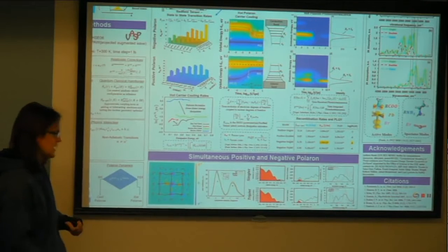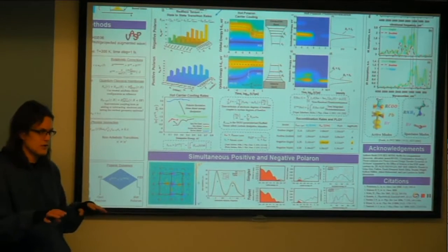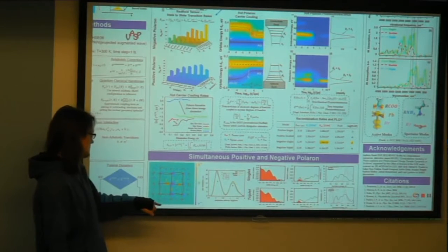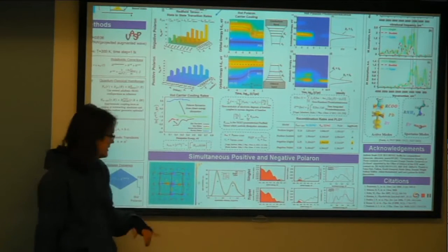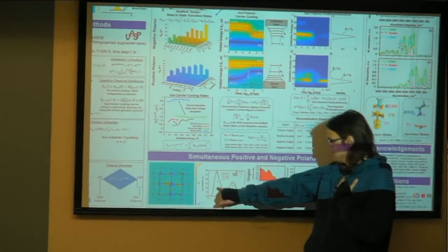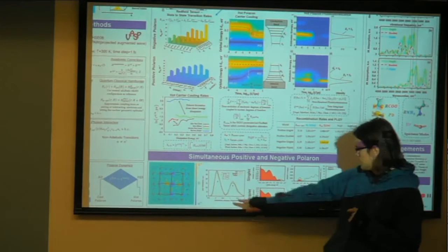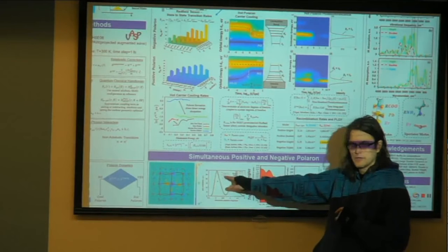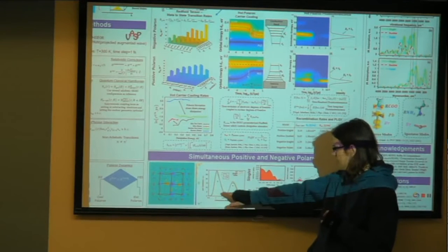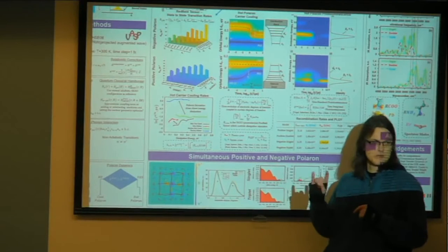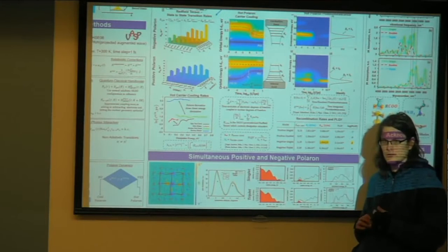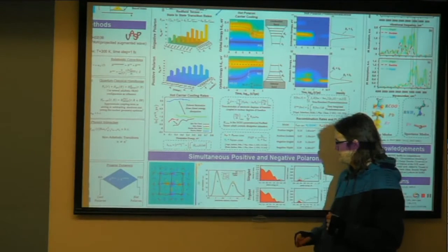And so instead of having a uniform charge throughout the whole box, throughout the whole model, we have, I guess, either a heterogeneous combination. So we put both charges in the box, but we compute radial distribution functions again. We look at the same bonding between the lead and the bromine, and instead of just seeing one peak or the other peak move, you see differences in geometry for both the lead-bromine and the bromine-bromine coordinations.